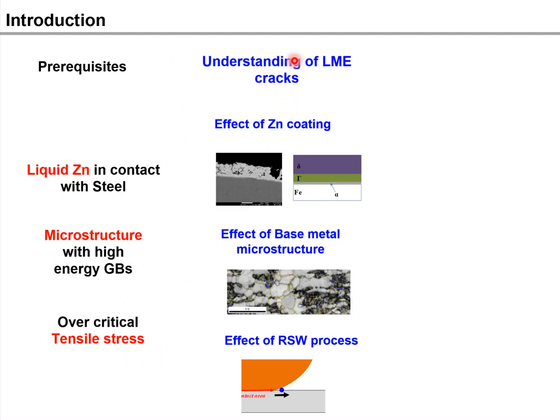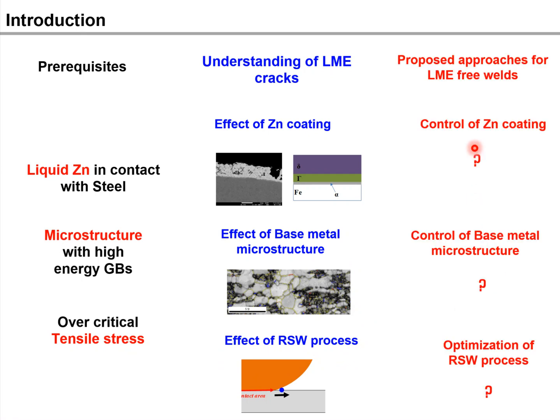For a better understanding of liquid metal embrittlement cracks, I will try to explain the effect of zinc coating on the LME cracks. Secondly, the effect of base metal microstructure on the LME cracks. And lastly, the effect of resistance spot welding process on the LME cracks. After that, I will propose feasible approaches for LME-free weld: first, control of zinc coating; second, control of base metal microstructure; and lastly, optimization of resistance spot welding processes.